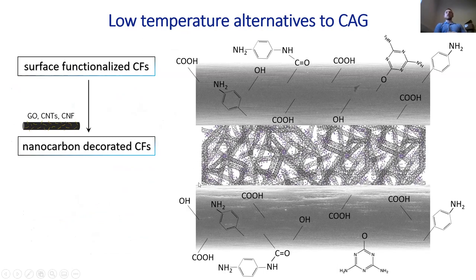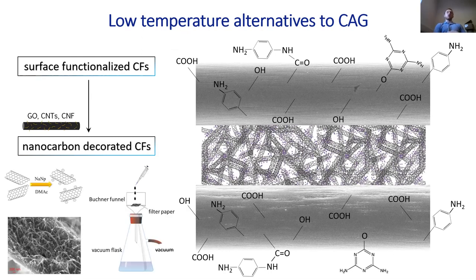The second step would be deposition of nanocarbons, or particularly carbon nanotubes, and it should be emphasized that this step does not attempt to replace carbon aerogel and achieve similar surface area values, because these materials are much more porous and much less surface area contributing. The main goal of depositing carbon nanotubes in the space between the carbon fibers and on their surface is basically giving sufficient increase of the surface area and conductivity for later deposition of pseudocapacitive elements. The route which I try to use for this purpose is reductive dissolution and deposition of carbon nanotubes.